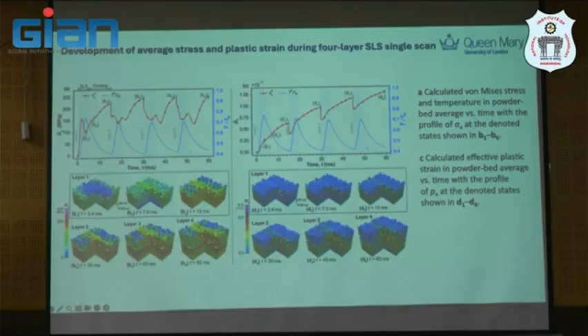So it's quite uniform, but uniform not in the sense that it doesn't jump around a lot, but it's actually oscillated around this 200 megapascal, whereas the plastic strain actually starts building up like this. But there's a phenomenon which is interesting, because normally you would not get plastic strain going up all the time, right? Because it is permanent deformation, it won't be able to go back. But there is something interesting that we can discuss when we get inside, based on the processing technique here.